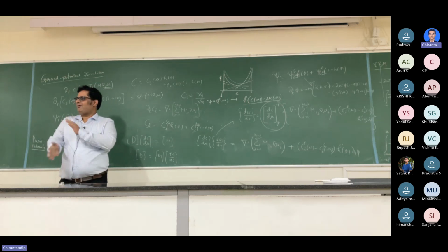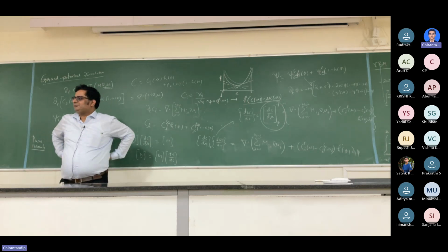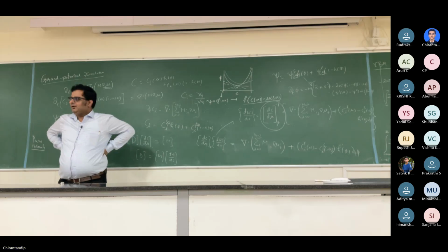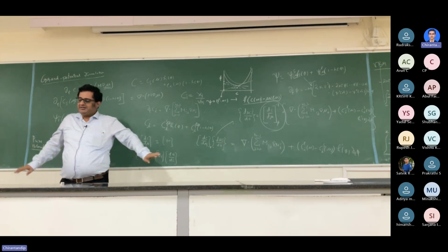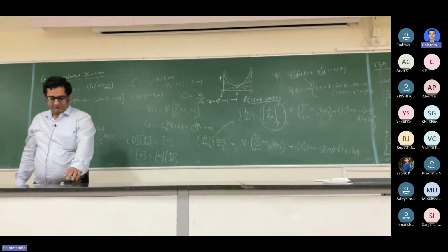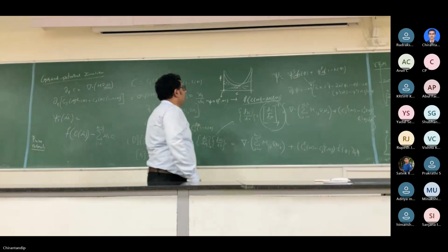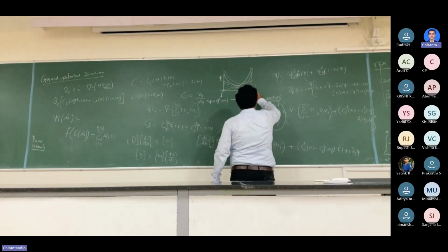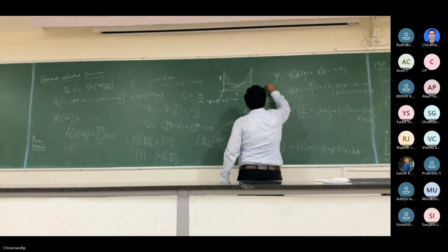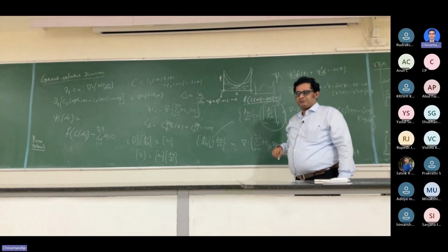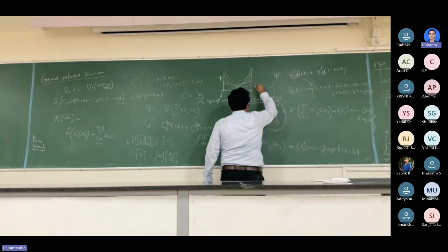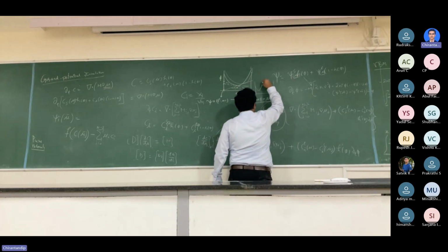It's very simple to understand why dmu by dc will be invertible in a multi-component space. dmu by dc, as I said, if it's a single valued function, that is understandable. Always concave, you will always have it. But that is not a limitation. I am always at liberty to, even if I have a miscibility gap, locally convexify my function. Not deliberately, but by choice. Because remember, I'm not going to functionally do this,